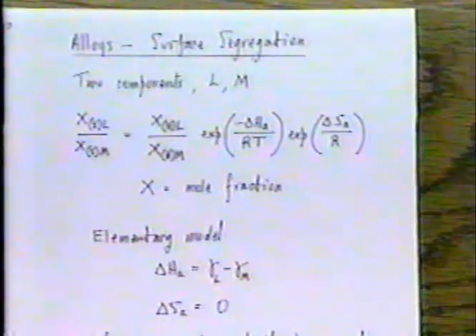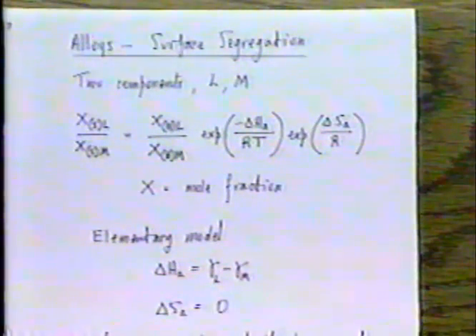Very briefly, we'll make a start now on saying something about alloys, but we won't be able to get past the first sheet or two, but it'll be useful to get going. Ultimately, I'm going to say something about the structure of dispersed alloy particles, that is, small alloy particles, but we need to begin by discussing something of the surface chemistry of alloys in general. The most important thing we need to address is, if you have an alloy of two components, I've called them here L and M, one usually cannot assume that the surface composition of the alloy, irrespective of whether this is a small particle or a large particle or massive metal, is the same as the bulk composition, and in general it will not be so.